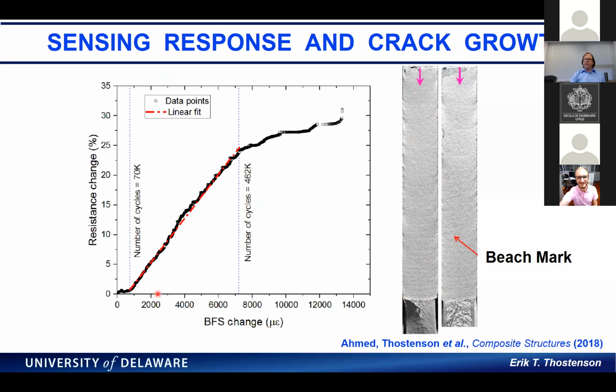And certainly here you see the resistance change of the specimen due to the nanotubes, and then the back face strain change, which measures our crack length. The number of cycles, you see it's very linear. And then once we hit 462,000, we actually started fatiguing the back face strain gauge. So it didn't really give us good data after that, but I think it's interesting that we were not fatiguing the resistance change.